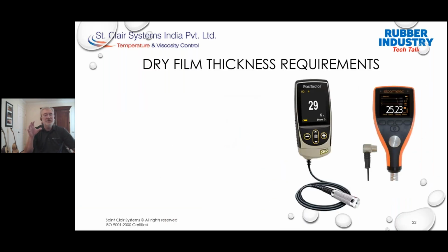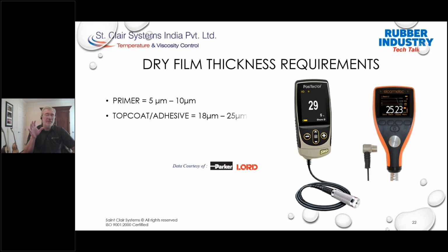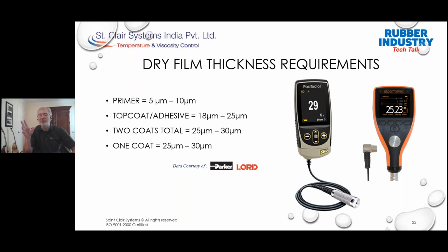So we have to establish our desired dry film thickness range. Okay, now on the data sheet provided by Parker Lord, the primer should be applied at 5 to 10 microns as a dry film thickness. Now the top coat should be applied in the 18 to 25 micron range for a total dry film of 25 to 30 microns. Likewise, if you're doing a single coat, it too should be applied in the 25 to 30 micron range. These are the optimal film builds to get good bonding and optimal film strength.